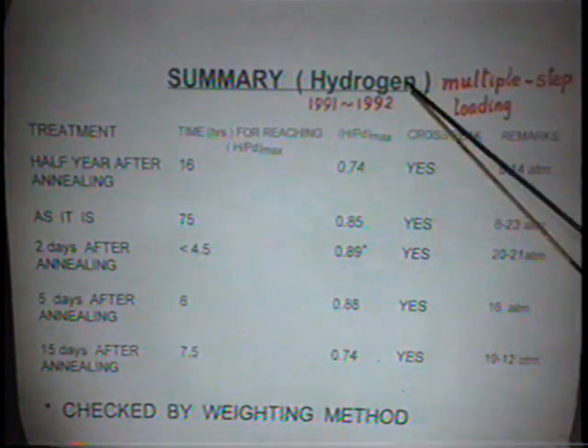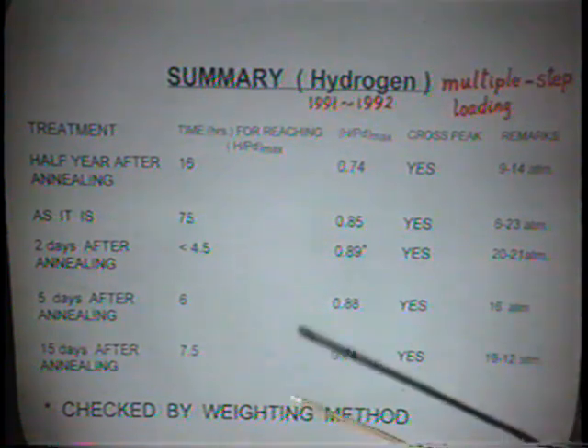When we use hydrogen to reach this, then we switch to the deuterium. But he failed in loading the deuterium into the palladium to cross this peak. He couldn't, because the pressure is too low. Then he graduated. The next student came, he used the deuterium.